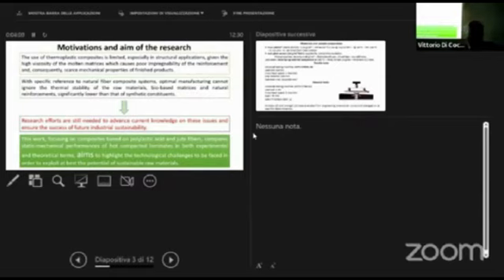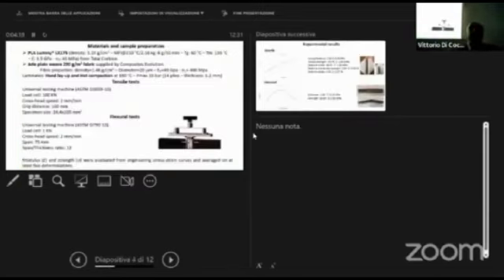The aim is to highlight which are the challenges from the technology point of view that you have to face in order to have a finished product with properties that are competitive with composites based on synthetic raw materials. So we worked with the typical processing approach, that is film stacking and hot compacting with the press. We combined the polylactic acid with the jute fiber fabric.